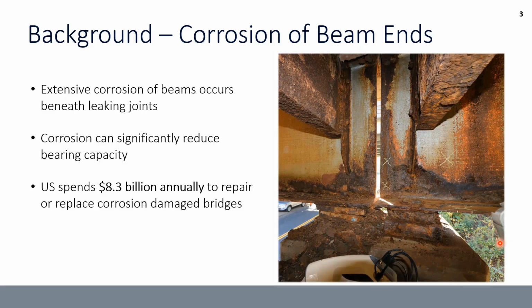What happens is the water and debris pile up in the bottom flanges, the water comes down, splashes, and usually the typical pattern we see is the bottom 6 inches or so of the web is corroded and quite a bit of section loss on the flange, and sometimes 100% section loss on the bearing stiffeners.